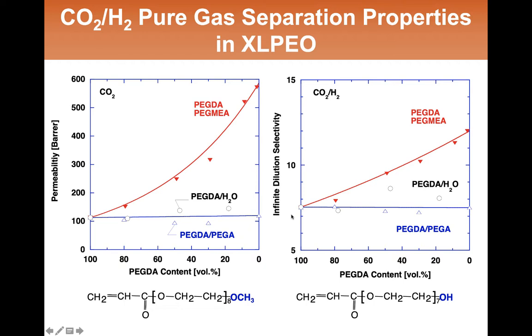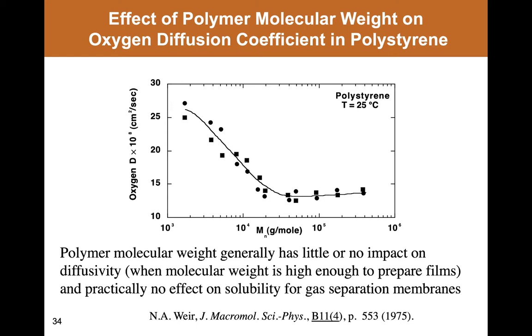In addition, selectivity also changes, and in the case where the glass transition temperature was changed very little due to changing the polymerization conditions, you see very little change in selectivity. In the case where the glass transition temperature changed, molecular mobility changed, then selectivity changes as well. Another phenomenon that you'll often find asked about is the effect of molecular weight on transport